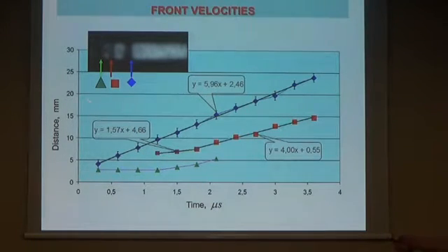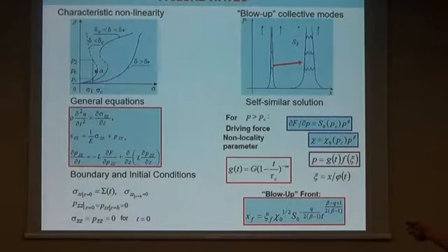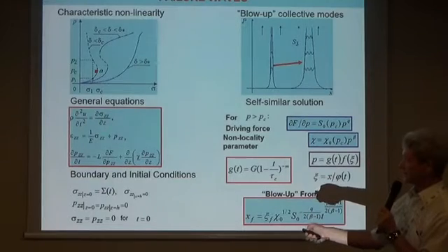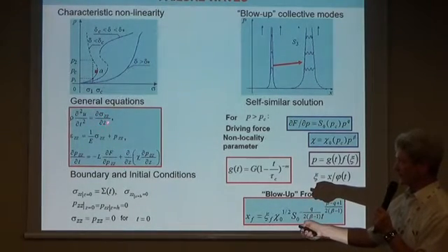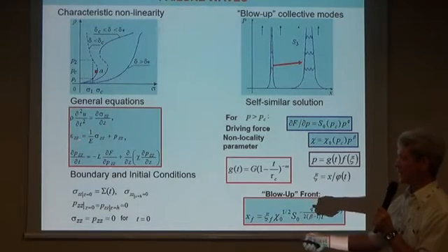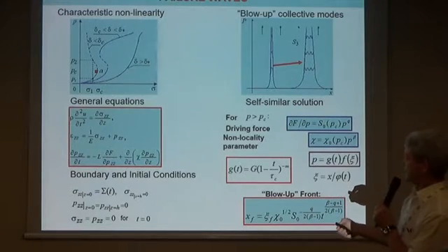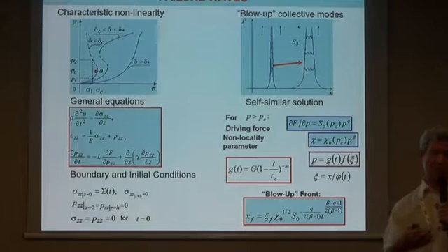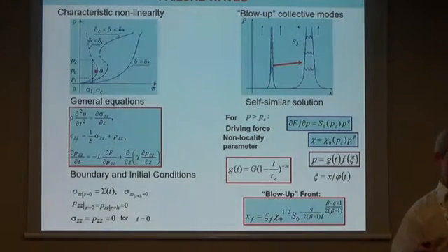When we plot this distance versus time, it corresponds to the front of stress propagation, the front of the failure wave, and this is the front of the end due to the collision. You see, we have a constant delay of the elastic front from the front of the failure wave. It exactly corresponds to the similar solution with blow-up nature, and this is a mathematical statement for the failure wave scenario when we have elastic material with defects and kinetic equation of defects. And it means that when we pass this critical point, we could excite, in different situations which are related to the stress amplitude, different scenarios of failure wave.